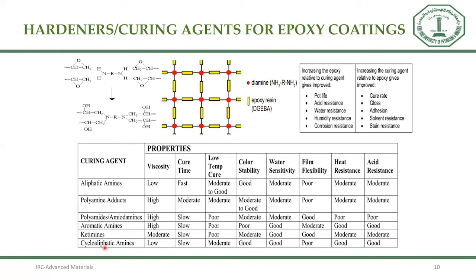And after selecting the amine and epoxy resin, now we need to fix the ratio between them. To fix the ratio between epoxy and hardener, we want to know two things. The first is the amine hydrogen equivalent of the hardener, as well as the epoxy equivalent weight. By knowing these two, we can predict how much amine and how much epoxy resin we should take in the ratio.